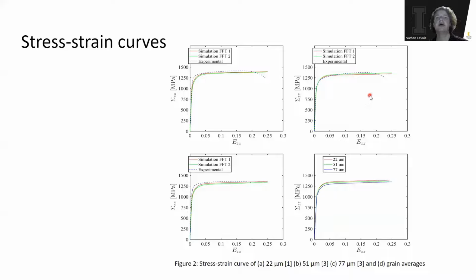In the 51 micrometer crystal, you can see the only difference is that there's a very high correlation at the yield point as well, meaning that this is very well modeled, but it can still be better. It can still have a higher correlation. The model Inconel 718 crystals have a moderate overall correlation with the experimental data, and this will be optimized later. The simulations also showed a correlation between grain size and a weakened reaction to stress, which is consistent with experimental results. You can see that 22 down to 51 down to 77 under the same conditions, it gets weaker and weaker as the stress increases.